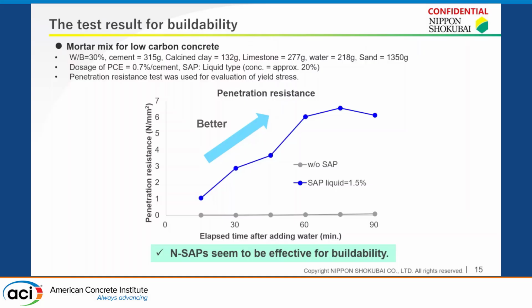This graph shows the mix with SAP liquid showed improved yield stress behavior compared to the mix without SAP. So further study is needed, but we believe our new SAP can improve buildability for 3D concrete printing.